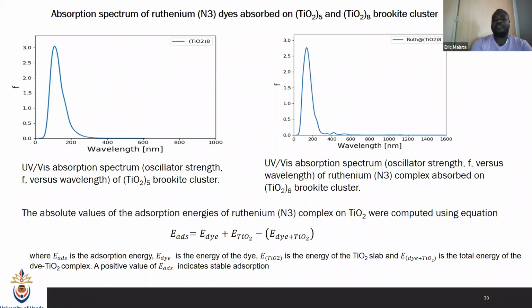And then we look at the absorption spectrum. If we look at the Ti5, this is without any dye, and here is with dye. I think I made a mistake, it must be 8 here, it doesn't have to be 5. Because I'm comparing 8 and 8, we can see that when we include the dye, we also see the absorption here still improve the absorption from 400 to 600. But theoretically, what we want is to move from 400 to the near infrared, about 700 there.